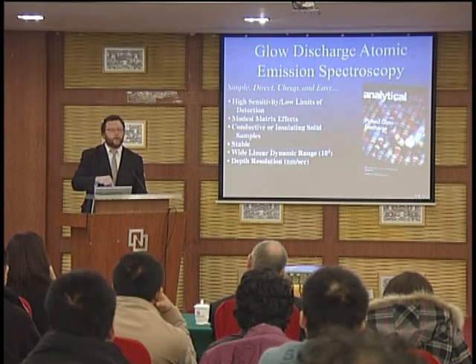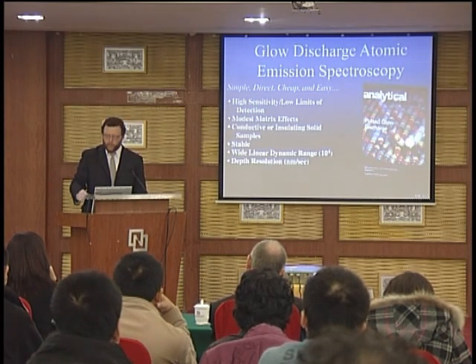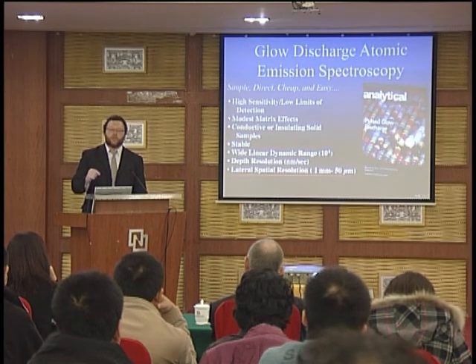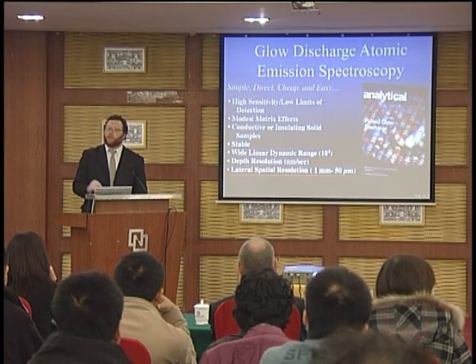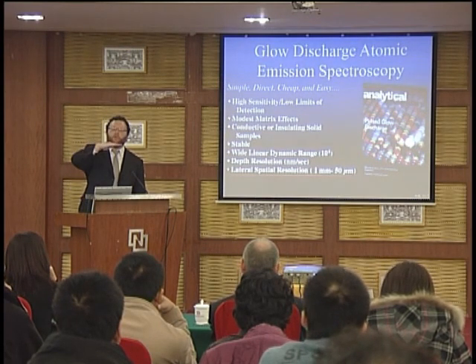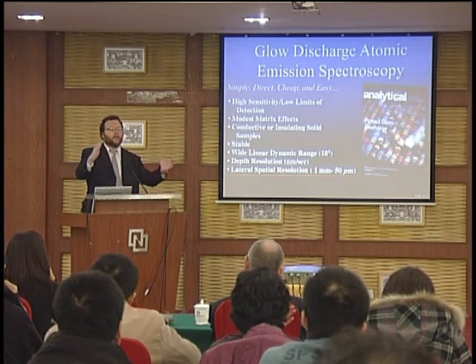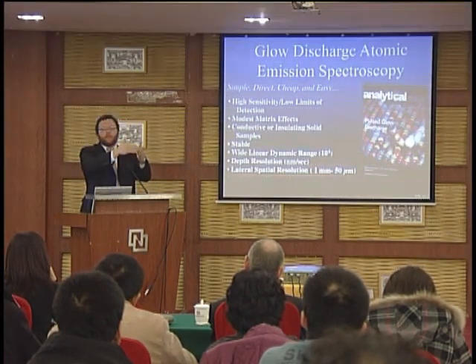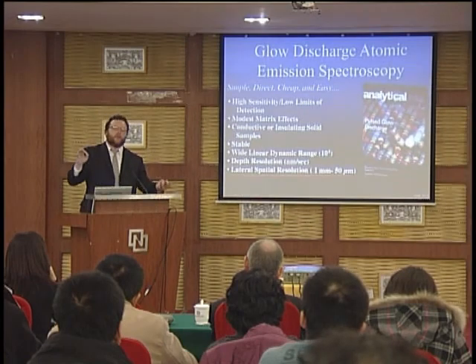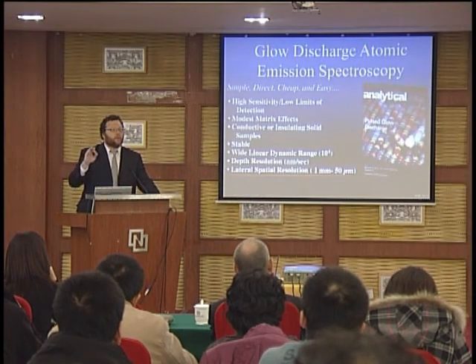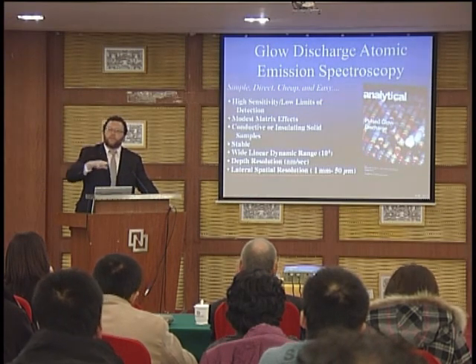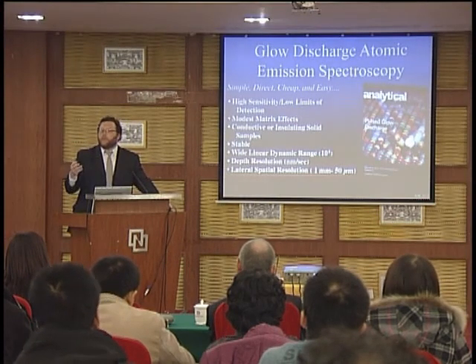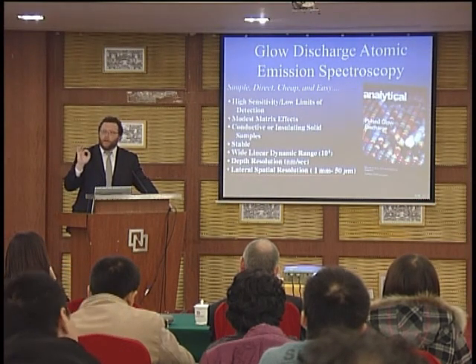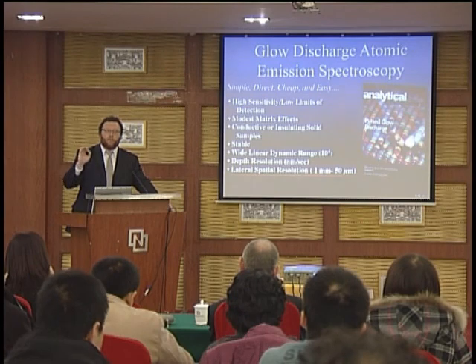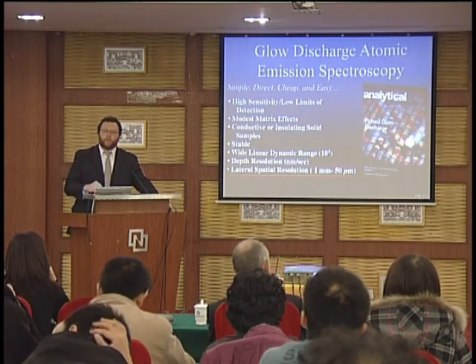Now in our laboratory, we really want to add another bullet point here. We'd like to be able to say that glow discharge also has lateral spatial resolution. In addition to going through depths of layers, we'd like to say that you can get a good idea of what might be on the X and Y axis there. But the final goal is maybe making a three-dimensional model of what the surface looks like. A lot like what you would get with SIMS or something like that, but doing so a lot more cheaply and with a much wider multi-elemental response.